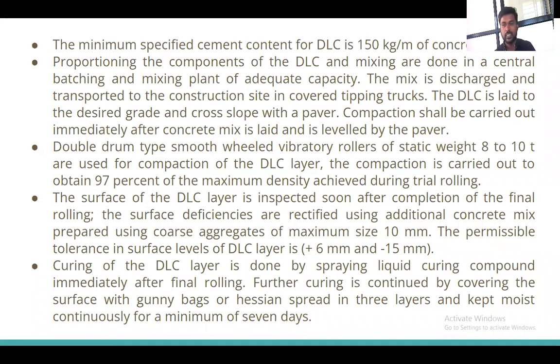The DLC is laid to the desired grade and slope with the paver. The compaction shall be carried out immediately after the concrete mix is laid and leveled by the paver. For the compaction of the DLC, double drum smooth wheel vibratory rollers or static rollers of 8 to 10 tons are used.